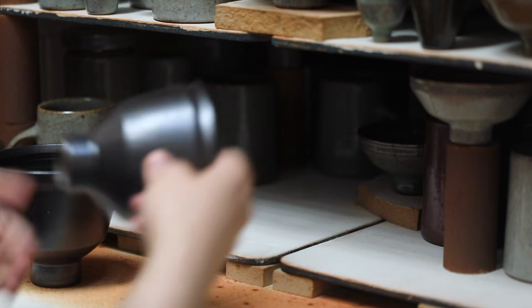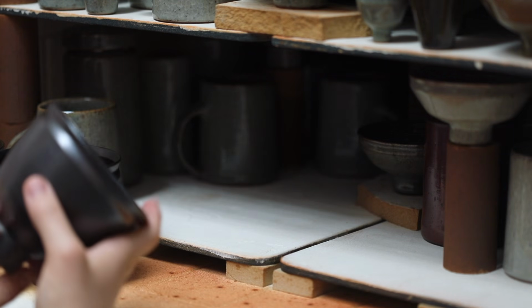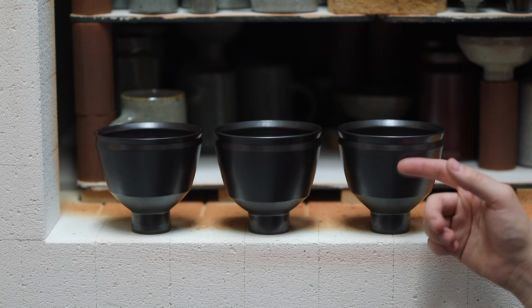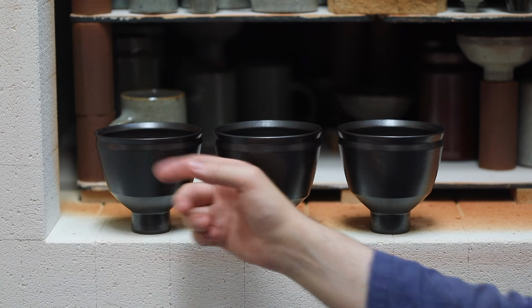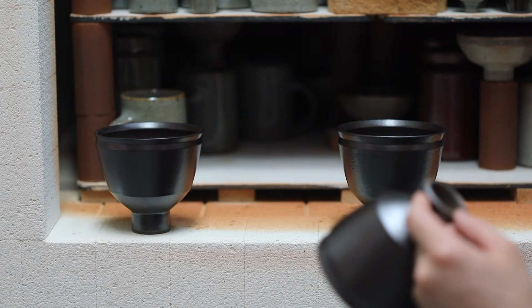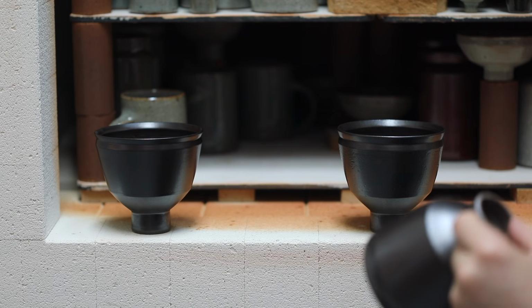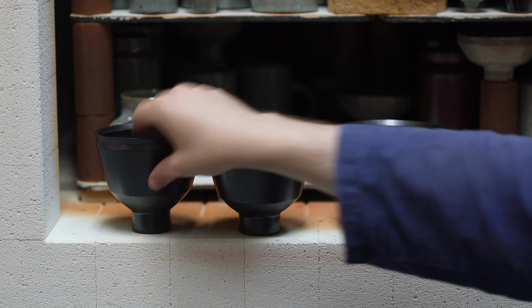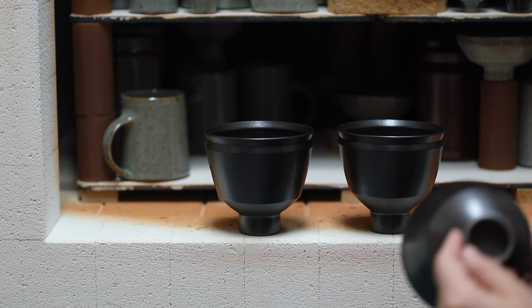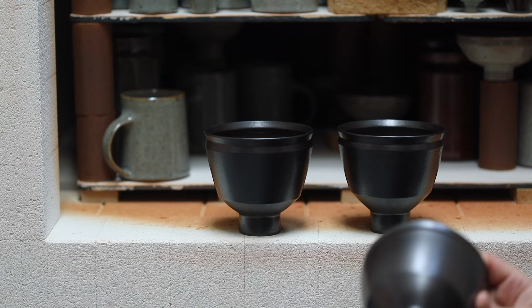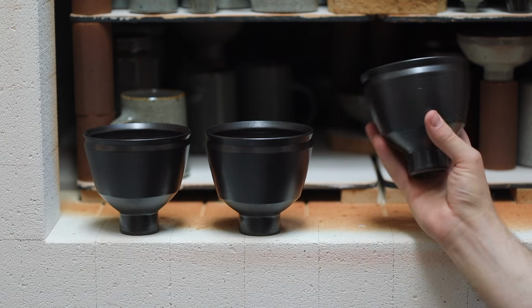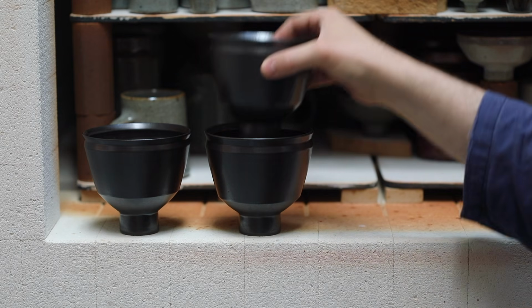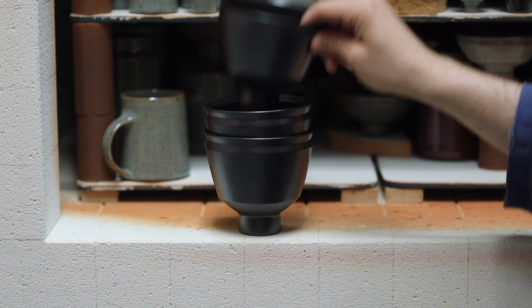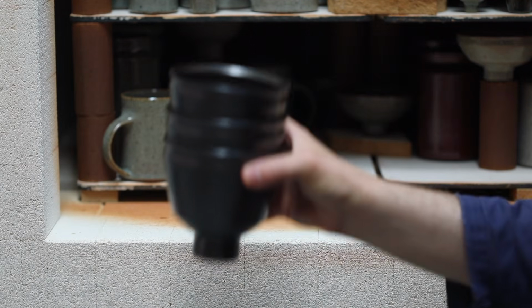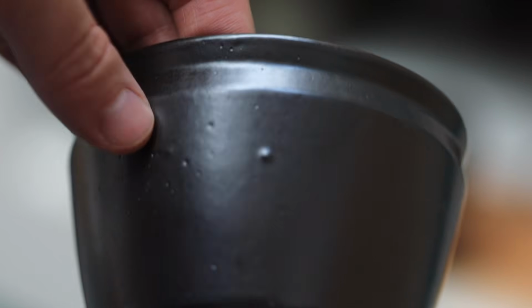The only immediate thing I noticed is that the bare clay on the bottoms of these isn't really black, and there are some subtle differences in terms of the surface quality, which I think has come from my mixing of the clay. One of these was thrown from purely the black, another was mixed down by 50%, and another by a third. And I think in both of those cases, it's created a certain level of texture on the surface. Texture can of course be rather nice in some cases, but with these, and I will show you a close-up, it sort of feels a bit like a mistake. It isn't intentional enough. One of them has these small bloating marks around it, and a few tiny pinholes, but I almost don't mind that very much.